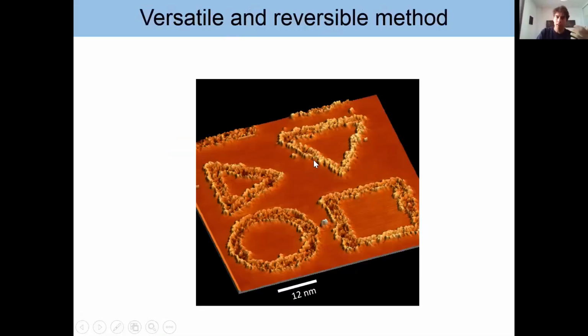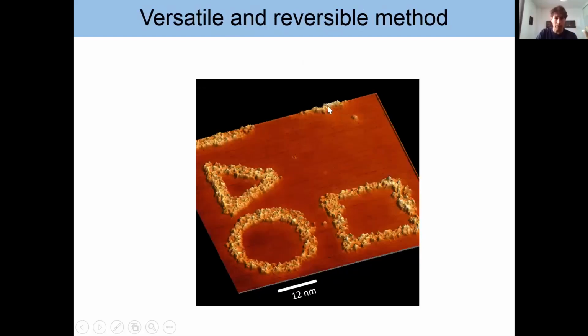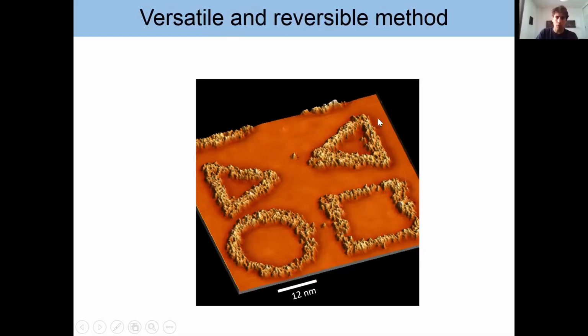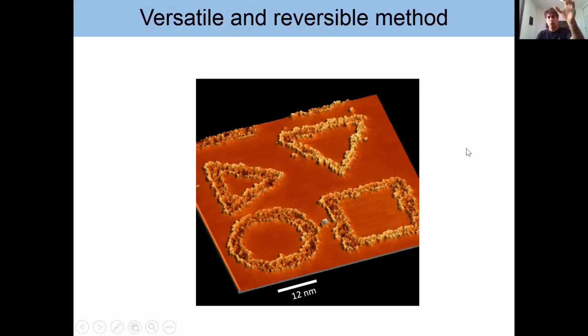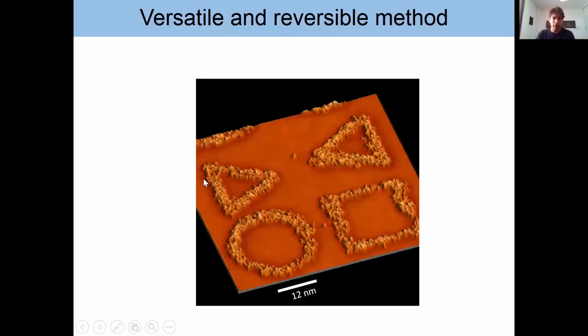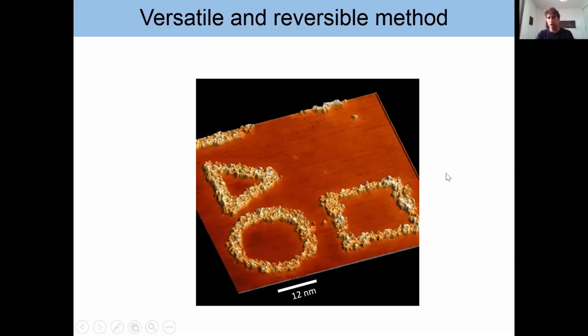So let me tell you more about our method. It really works 100% of the times, and it's very versatile. We can make the patterning in any direction. You can see here rings, squares, triangles with different orientations. Those are features of something like 10 nanometer size, and we can even erase them. Here I'm erasing this triangle, and then I rewrite it in a different direction. So let me show you the animation. We erase it, we rewrite it, and essentially the other structures are not modified. So this works very nicely.